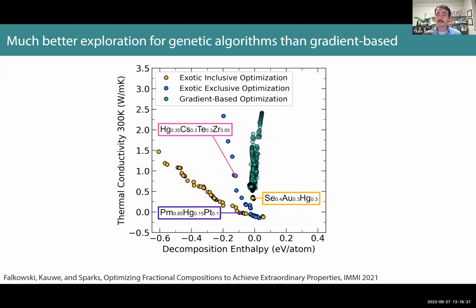And what I think is really cool is when you start comparing this sort of black box optimization to the gradient-based approach, which again was style transfer. It was fixing a chemistry and trying to just get the right ratio. So in teal, the light green here, you see after many, many iterations of our neural network tweaking the formula, we were able to slowly learn how to decrease the thermal conductivity of this material, but it was locked into a chemistry, right? And so it did a bad job of exploring the solution space, whereas the genetic algorithm in very few data points here was able to explore it. Now, you might be tempted to think that because there's very few data points that means it was fast. It was not. Genetic algorithms are slow. Neural networks can be fast.